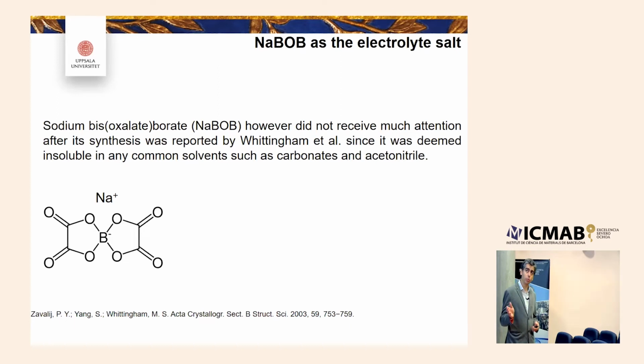The other option is BOB, which lithium BOB has been a common lithium salt for lithium-ion batteries. But when we looked at the literature, we could see there were no papers actually using sodium BOB. There was only one paper by Stanley Whittingham showing the synthesis of sodium BOB and its crystal structure, published in 2003, but no electrochemistry, no battery cycling.